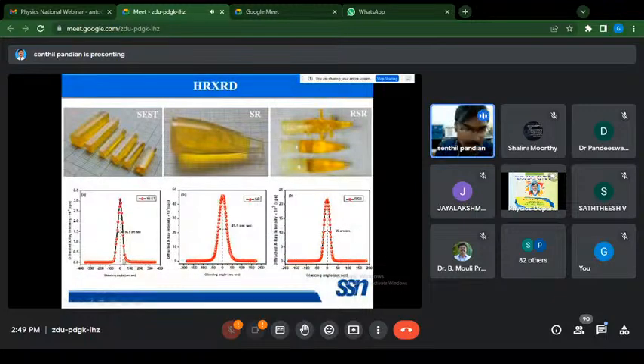In order to identify the crystalline perfection of the grown crystal, we have carried out the HRXRD, high resolution X-ray diffraction measurement: 56.5 arc seconds for the conventional method growth, and 45.5 arc seconds for the SR method, because here we have avoided the growth sector boundary, solvent inclusion, and micro cracks in the SR method grown crystal. So compared to the conventional method grown crystal, the SR method grown crystal has higher crystalline perfection because of the absence of growth sector boundaries, solvent inclusion, micro cracks, and milky opaque regions.